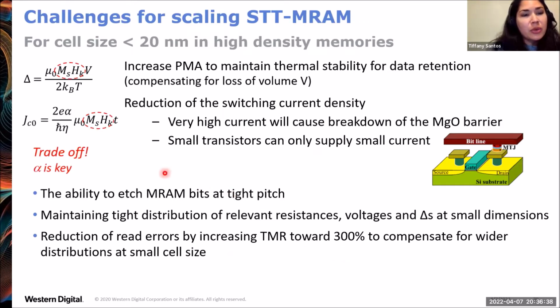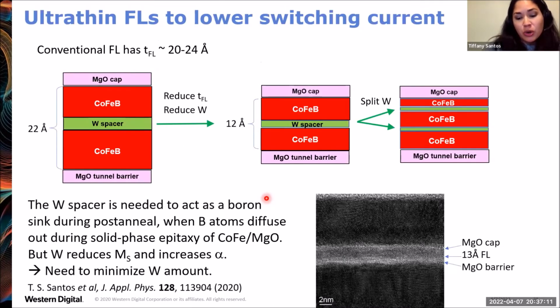So the first one I want to address here is this very challenging trade-off for anybody working on MRAM: the trade-off between thermal stability and low switching current. Now, if we want to increase thermal stability by increasing MS and HK, that also is going to increase your switching current. For that reason, the damping parameter here becomes key. And one way that we have worked to address this in our research at Western Digital is to engineer free layers that have low switching current. And I'll give an example of that here now.